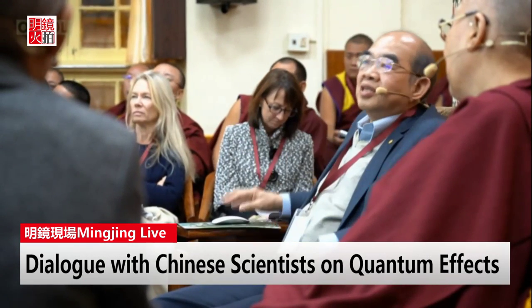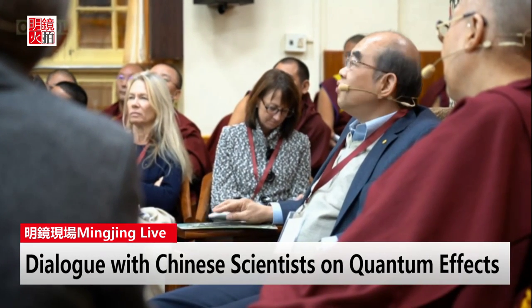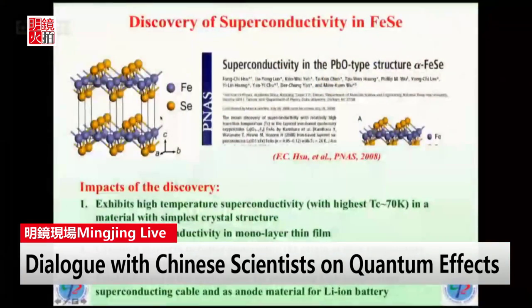So in 2008, we found this interesting new material. It has a similar feature: iron, also a d transition metal like copper, with selenium. Selenium is in the same column as oxygen, right? With one layer here, and you continue stacking on, this material becomes a superconductor. So it's a very simple structure, okay?